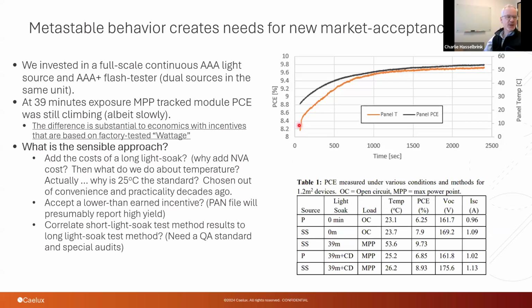But this does beg the question, if we are seeing, in fact, a positive temperature coefficient here, which we have seen in certain temperature regimes with our own product, actually, we have seen that in the past with some of our product and some of our lab samples, I should say. We see a positive temperature coefficient, and if that's the case, then you'd actually be incentivized to be reporting it at a higher temperature, right? And instead of a lower temperature.